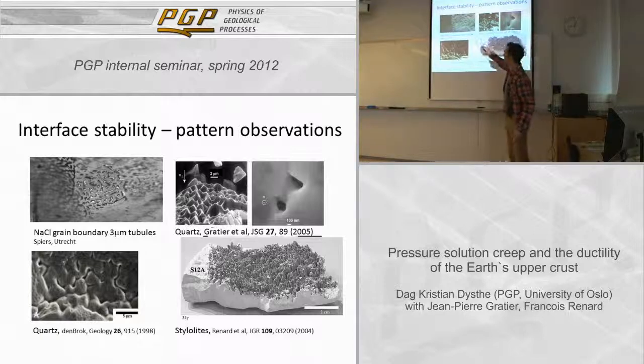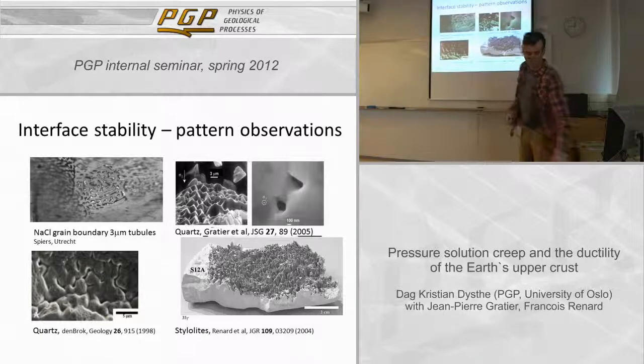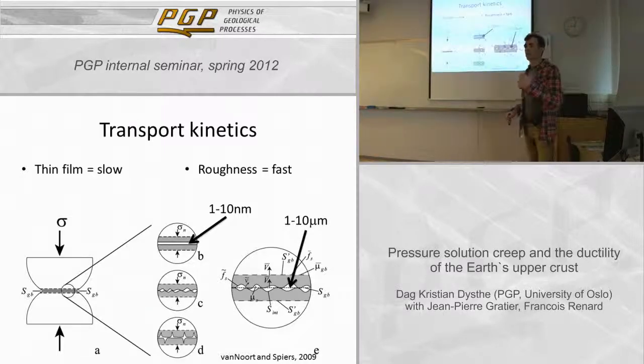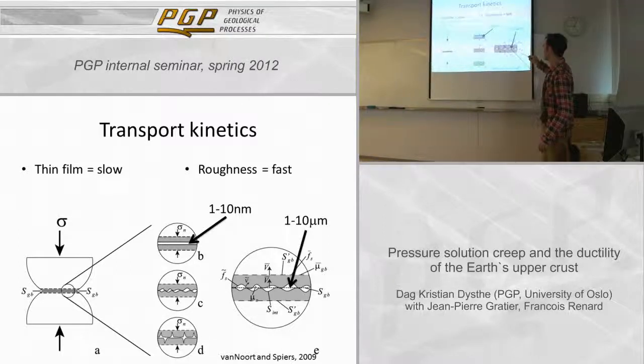There have been several types of observations after doing pressure solution experiments or in nature. You take them apart and you map out what used to be the grain boundary that was active in pressure solution, and there are clearly observations that there is often a roughness. Now, in this case, we're talking about 1 to 10 nanometers. In this case, there are channels of the order of 1 to 10 micrometers, which is three orders of magnitude larger. And so you can transport much faster out of such a network than there.